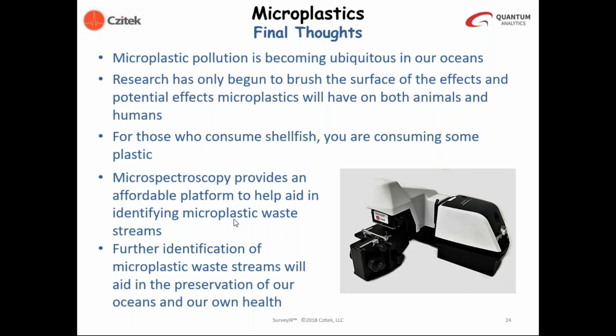Most of the time in an analysis is really taken up by the sample preparation aspects of it. And that can vary with the sample. Unfortunately, there's no single answer that's correct for how long that takes. Surprisingly, the manipulation of microplastics and microsamples in particular, once they've been isolated, if you have the right tools, it is really not that difficult to manipulate samples on the micrometer size scale and prepare them for analysis. So it can take several minutes to get a sample in a presentation that's appropriate for infrared microanalysis. If you want to use a rule of thumb, maybe 5 minutes is safe.